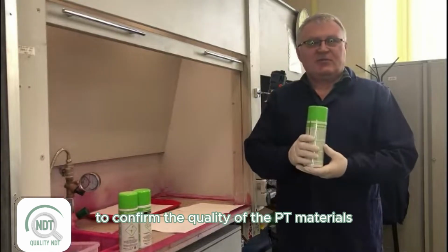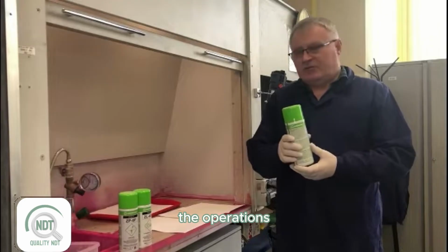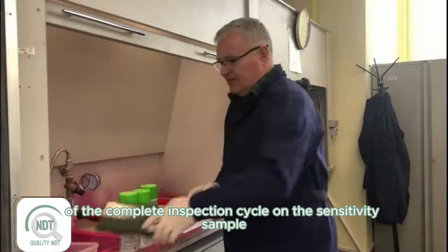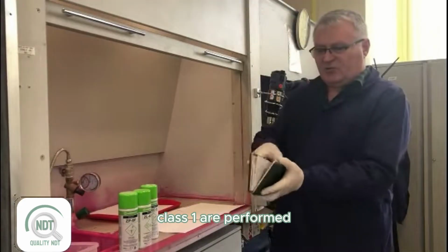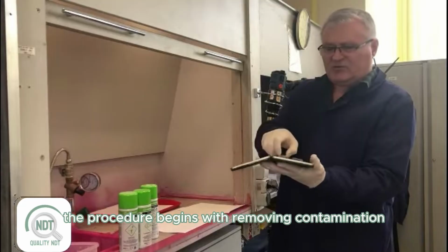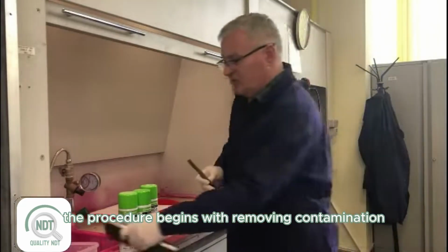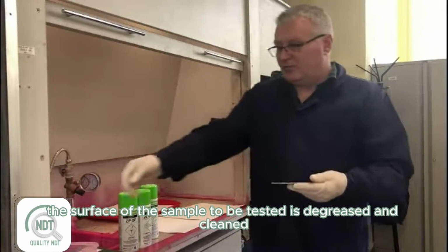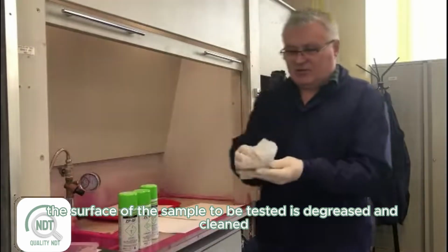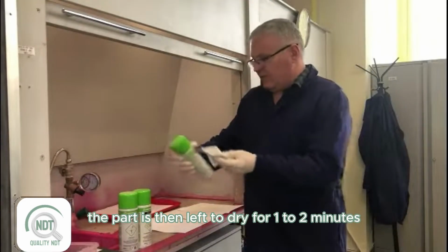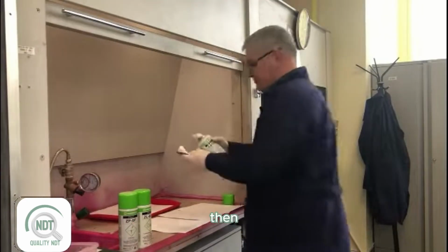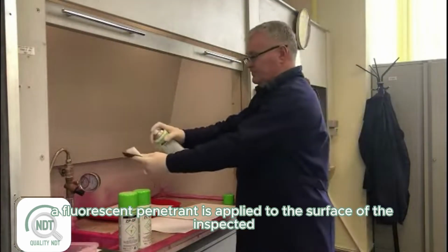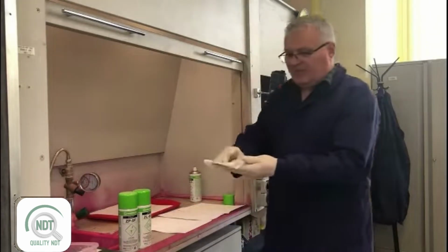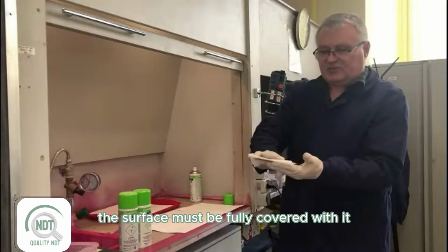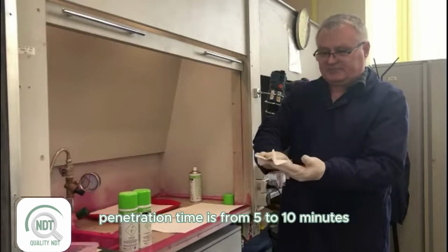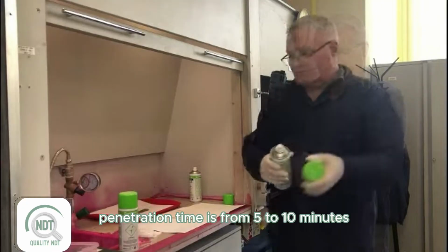To confirm the quality of the PT materials, the operations of the complete inspection cycle on the sensitivity sample Class 1 are performed. The procedure begins with removing contamination. The surface of the sample to be tested is degreased and cleaned. The part is then left to dry for 1 to 2 minutes. Then, a fluorescent penetrant is applied to the surface of the inspected sample. The surface must be fully covered with it. Penetration time is from 5 to 10 minutes.